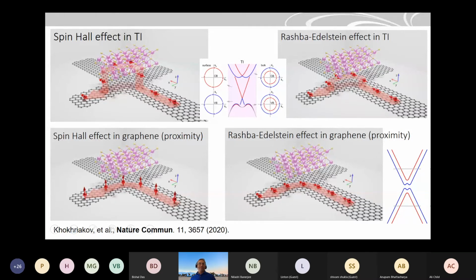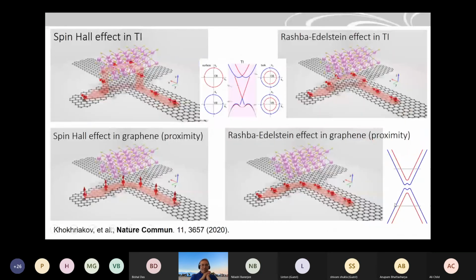What can be happening is two things: either the spin Hall effect or the Rashba-Edelstein effect in proximitized graphene. The spin Hall effect would give perpendicular spins, which we cannot see in our detection system because our cobalt, which is injecting the spin, is in plane. But what we see can be explained by the Rashba-Edelstein effect, because this gives in-plane spins, and this also should change sign, as I showed you. Okay, with this, maybe I can stop and take some questions.